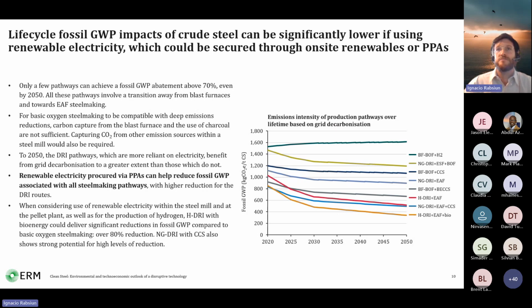You can see that that is particularly the case for the hydrogen pathways, the red and orange ones in this chart, because they are very electric intensive, not just to operate the electric arc furnace, but also to produce hydrogen. And you can see that by 2050, those three direct reduction pathways, the two hydrogen ones and the one with natural gas, but using CCS, reduce their emissions by quite a lot.